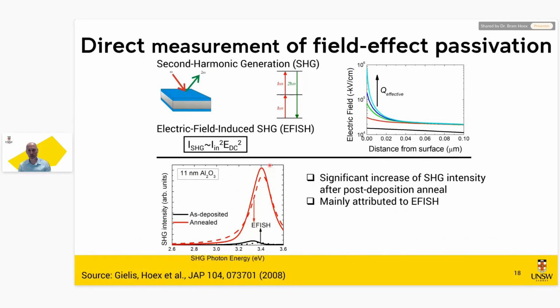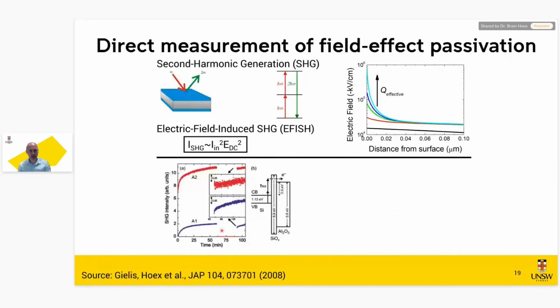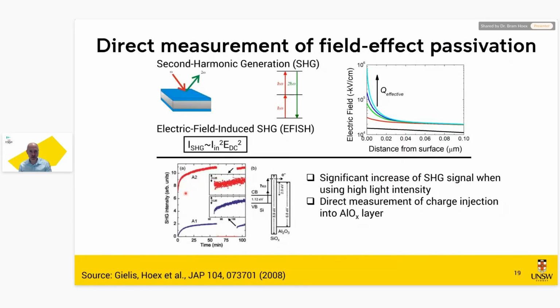So we had a non-contact way to measure electric fields. What we also saw in this experiment, and this is super relevant for this study, is that if we took a too high intensity laser beam, the EFISH signal increased. So we were able to kick electrons from the silicon into the ALOX and increase the fixed charge density. So we already demonstrated at this time that the fixed charge density is not necessarily a constant. You can increase it. And this is happening in UVID, because the more energy the photon supplies, the higher it's kicked up initially, and the higher the chance it actually can get trapped in the ALOX film. So we had here the first direct evidence of charge injection into ALOX.